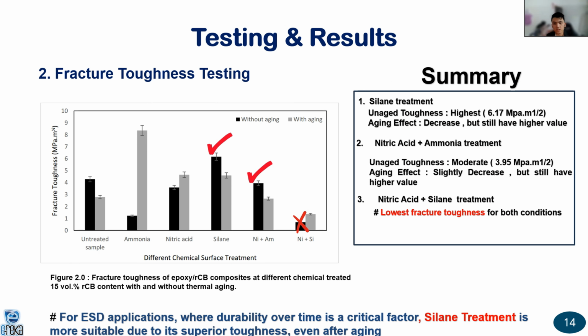Next, I will discuss the fracture toughness testing. Basically, this testing measures how well the material can resist crack propagation, and you can determine how much stress it can withstand before a crack begins to occur. Based on the graph, you can see that the nitric acid and the silane treatment show the lowest fracture toughness for both conditions. So if we want higher fracture toughness, the silane treatment is more suitable.